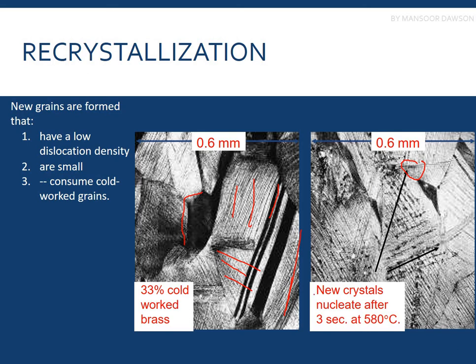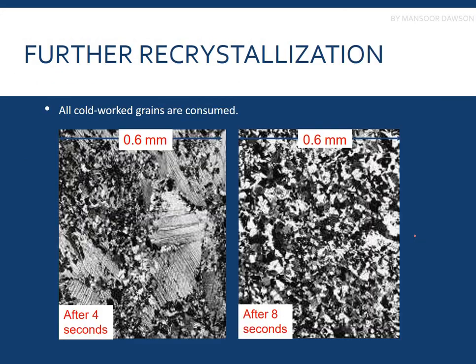This is a new crystal nucleated after 3 seconds at 580 degrees centigrade. This is a sample of brass. At 580 degrees centigrade, on holding it for 3 seconds, recrystallization is now observed. You can see that after 4 seconds, and after 8 seconds, new grains are being formed. So all the old grains are being consumed, and the new grains are being formed.